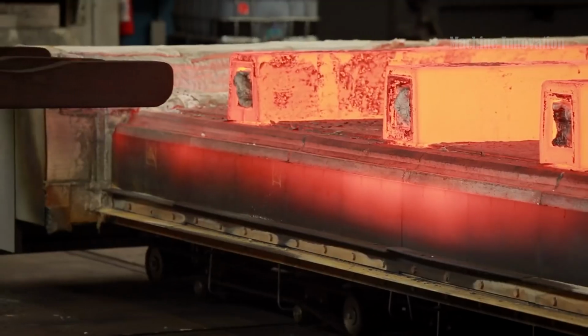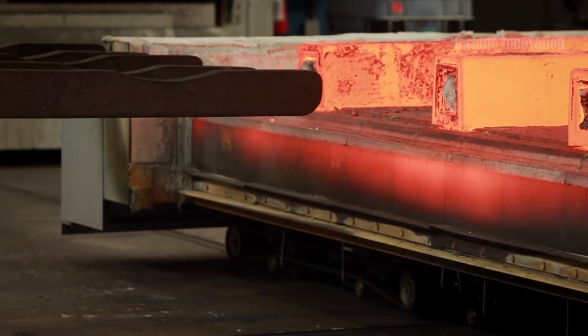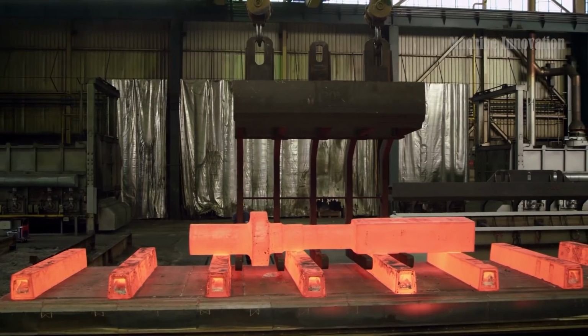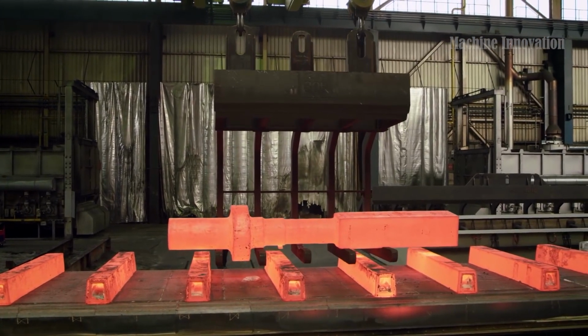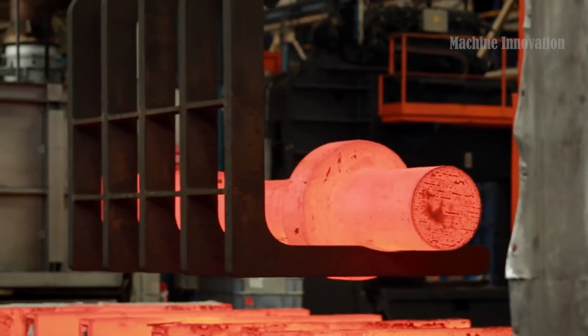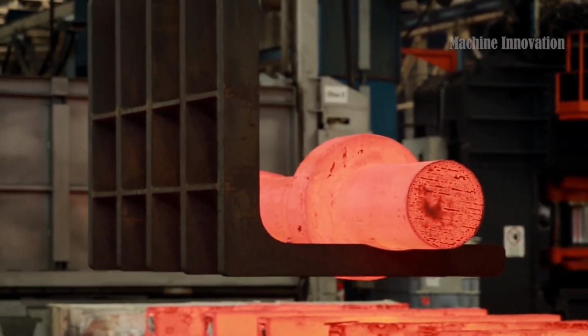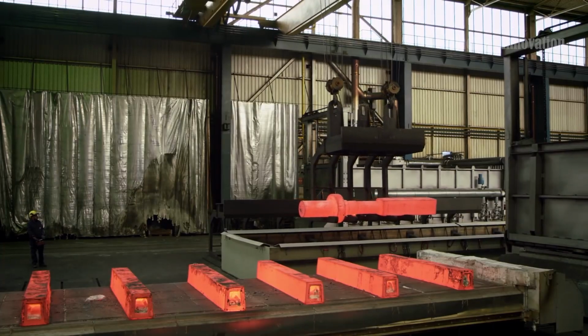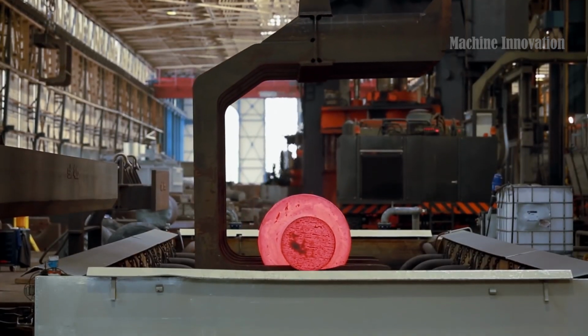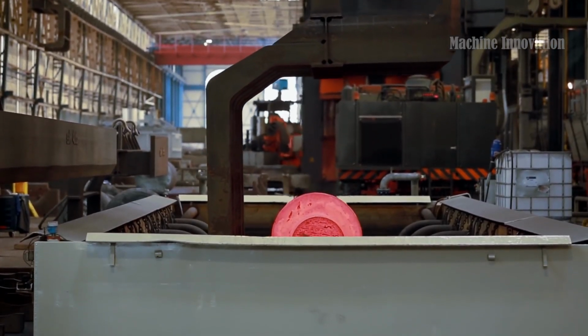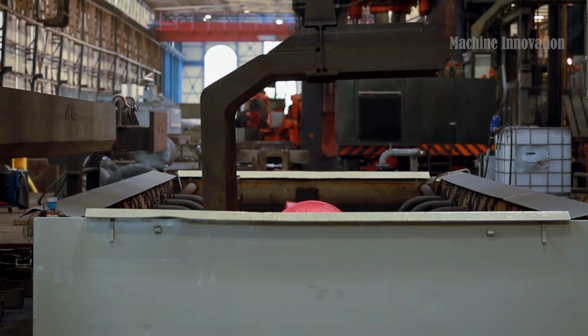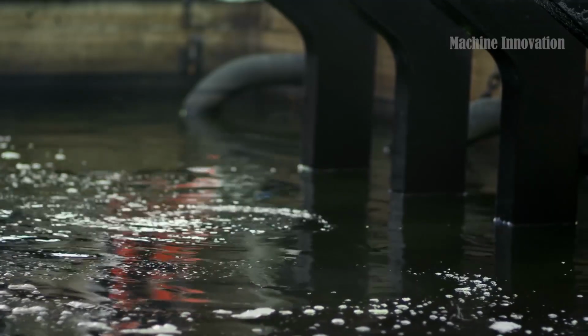and then rapidly cooling it by immersion in oil, water, or a similar medium. This heat treatment process hardens the material, making it more resistant to wear and improving its strength. The cooling rate is carefully controlled to ensure the crankshaft does not develop undesirable stresses or cracks, which could affect its performance during operation.